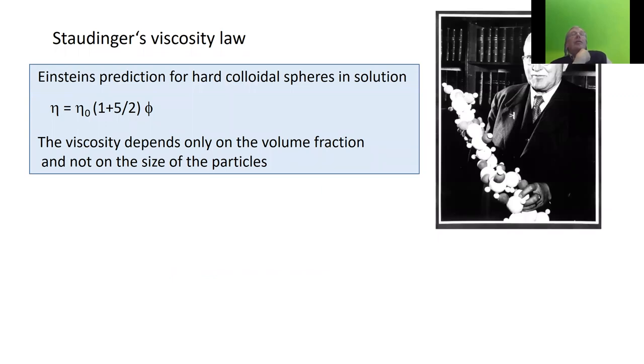Now, he also did a lot of viscosity investigations. He proved that when you take hevea and you hydrogenate it and you get the saturated polymers, the viscosity is not much different than before, so it worked nicely. So he tried to prove the existence of macromolecules by viscosity. In 1906, Einstein had developed his very famous viscosity equation, where he showed that the viscosity of a solution depends on the volume fraction of small colloidal spheres, not on their size, just on the volume fraction. This equation is valid for dilute solutions, and it became very successful in the whole field of colloids, but not on the molecular weight, not on the size of the particles.